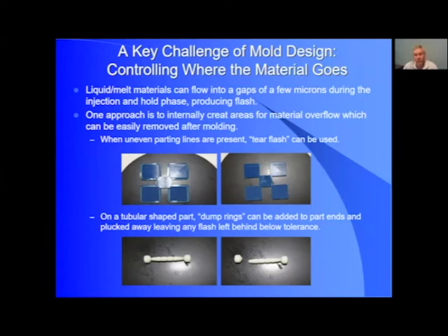So one approach is to internally create areas for material flow which you can easily remove after molding. And so we call this, as an example, tear flash. So in the upper left-hand photo, you can see this ridge of material around each of these four squares. This is a mold that is gated in the center. You can see a little vestige, a little dot in the center. That's where the molded material is coming in. It's flowing out through the thin square into these basically 4 simulated cavities. And so there's a little bit of an extra groove intentionally machined into the mold to allow for any excess material to flow once the desired part has actually been molded. And so you can basically peel that stuff away and be left with your final parts in the upper right hand.